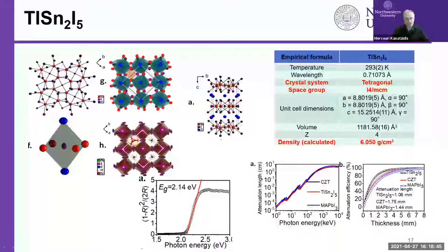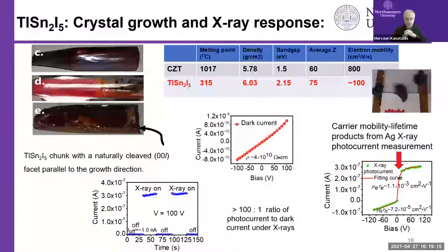Here's another material, thallium tin iodide. This is what we called an anti-perovskite structure. This is also promising. It has very high density, 6 grams per cubic centimeter, bigger than CZT. It has very good absorption compared to CZT. It has a band gap of 2.1 eV. So this is great. So we did some work on this. And here's some comparison. We can grow the crystals quite well. Very sensitive to X-rays. This is the X-ray response between X-rays off and X-rays on.